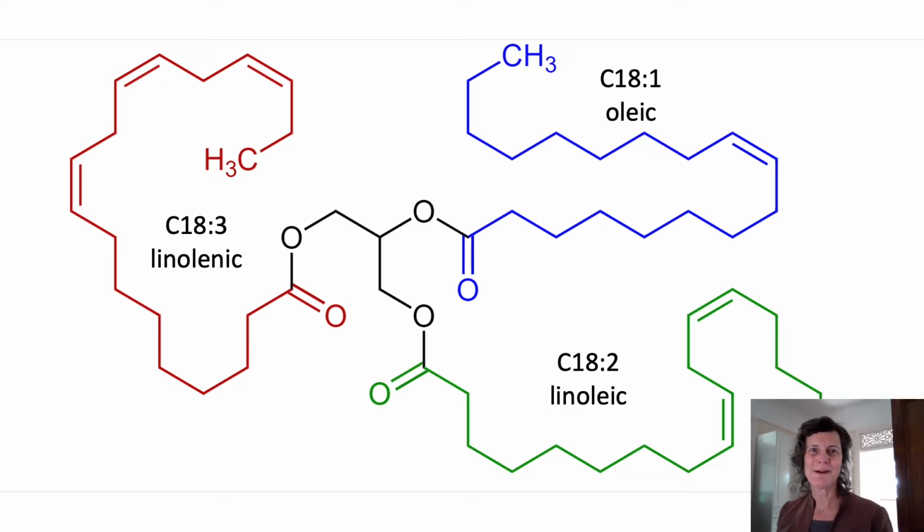First, it's helpful to be reminded of the triglyceride structures which form the basis of linseed oil. Constituent triglycerides are made up from a variety of fatty acids, most with chains of 18 carbons. The notional triglyceride molecule pictured here includes 3 different fatty acids, each with 18 carbons, and 1, 2, or 3 double bonds. The more double bonds, the greater the drying potential of the oil, as in the presence of air, the double bonds allow crosslinks to form, causing the oil to polymerize and dry.